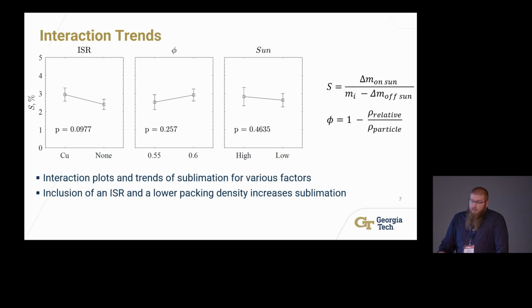The main takeaways for this is that the indirect solar receiver does make a statistically significant impact on the results. The porosity does show some significance, but we're still waiting on final results. And the same thing with the solar flux is we only have a few data points for the high solar flux, so I can't make any conclusions on the results for that.